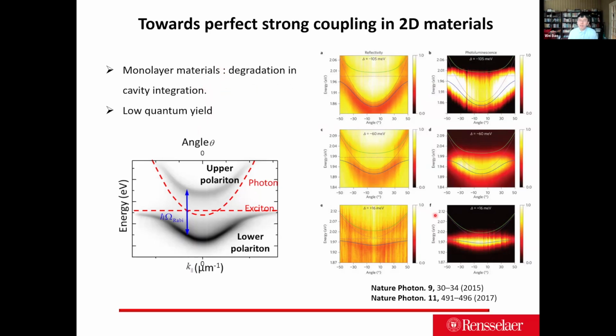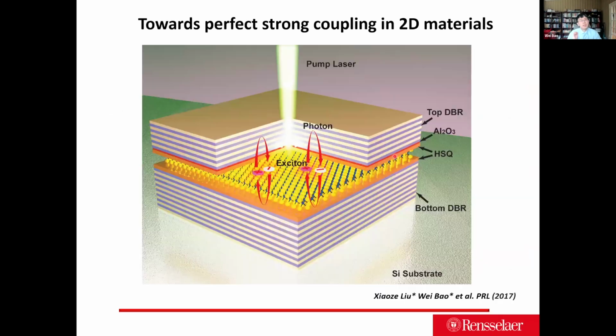So we typically see that even though they publish really good papers showing really strong Rabi splitting, the photoluminescence properties appear to be really broad in those 2D materials, and especially compared with gallium arsenide, the line width sometimes is not so ideal.